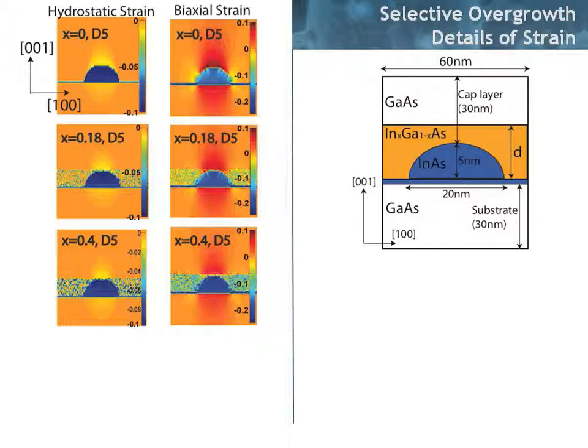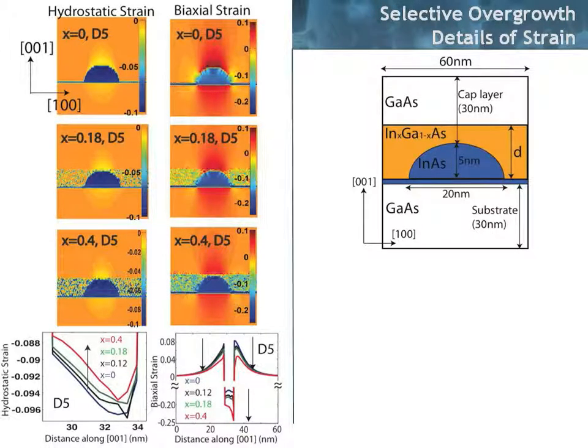You can show this in cut lines. If you cut vertically through these quantum dots, the hydrostatic pressure in the system changes slightly — not a whole lot — and gets a little bit smaller as you ramp up the indium concentration. For the biaxial strain in the same direction, you see that the strain inside the quantum dot is relaxed, and it really is also changing the strain inside. It seems to be relaxing the strain on top and the bottom as well, going down outside of the quantum dot.